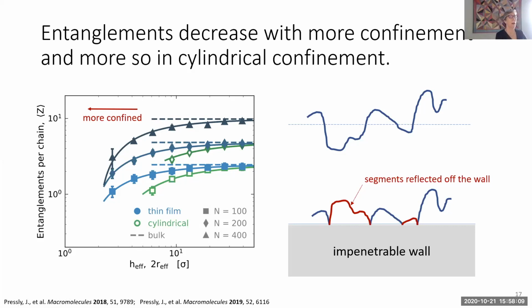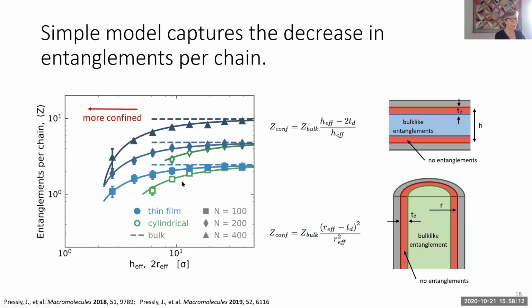Okay. Now, interestingly, those solid lines here are a very simple expression where we say that the center of the thin film or the center of the cylinders behaves like bulk, and then there's a region near the wall where there are no entanglements. And so that very simple expression gives us these curves that go through the simulation data very nicely, and we extract out this thickness, this depletion zone where there are no entanglements. And this increases with molecular weight, whether it's a thin film or a cylinder.